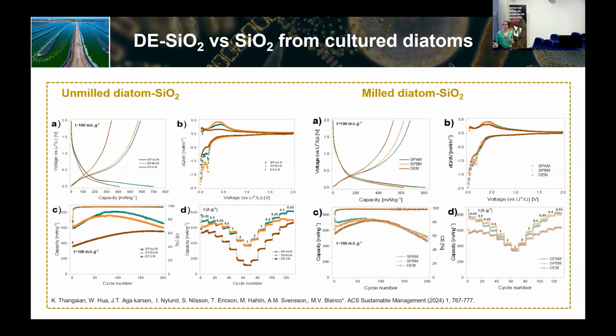And we see this is diatomaceous earth, non-milled material, and this is species A and B. So if this species A has a higher capacity, and also then we have the capacity decay after 100 cycles. That is like a magical number where everything starts to go wrong. That, of course, is attributed to silicon.